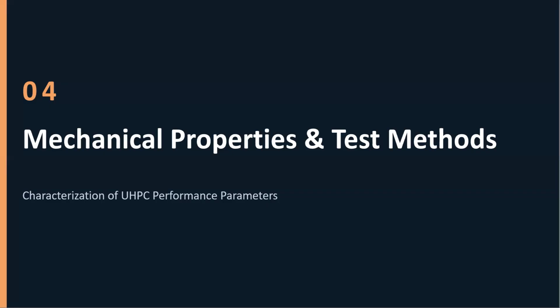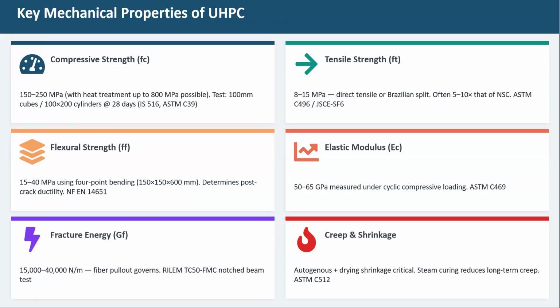And coming to the mechanical properties and the test methods, particularly we'll focus on the compressive strength, which is again tested on 100 mm cubes. That's a standard one that we are going to focus on. So anything with 100 mm cubes is more than sufficient. But if you are going with 150 mm cubes also, that is fine. But typically when we go with UHPC in laboratory testing, we'll go with 100 mm cubes. That's more than sufficient, with 100 by 200 mm cylinders also. That's as per the guidelines of the IS code as well as ASTM standards.